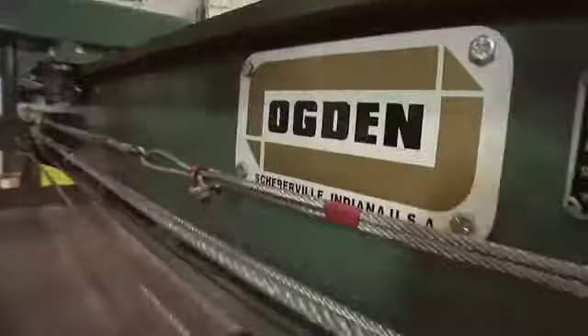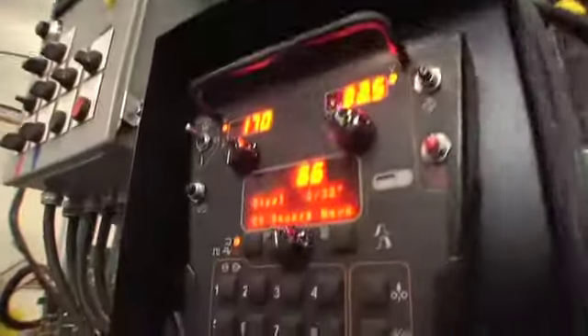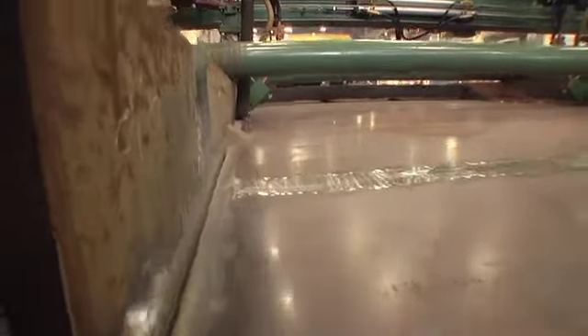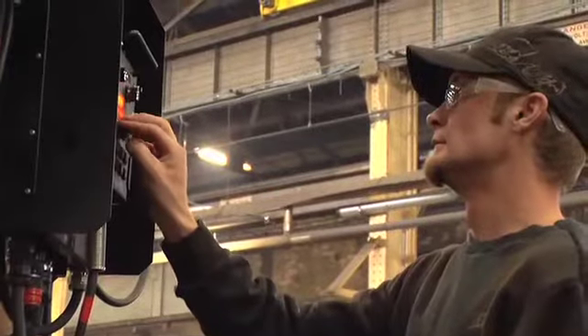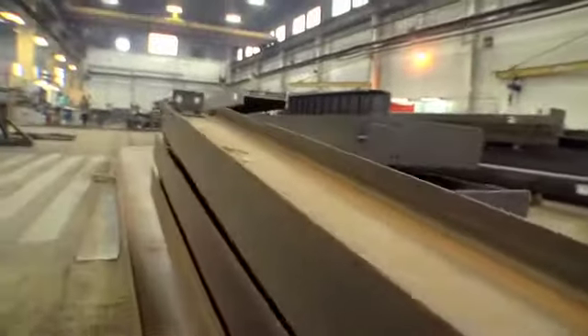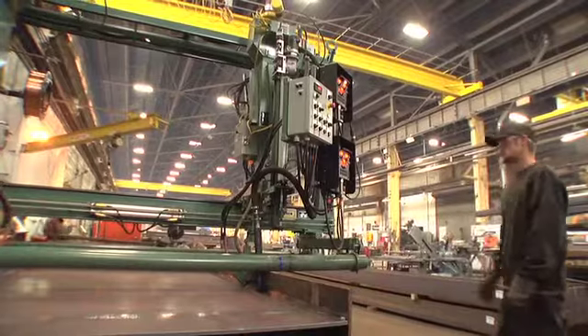They are PLC units. They're programmable logic controlled units that make up to 67-foot welds on this project, 5/16 continuous, with non-stop welding. With this technology, what it allows us to do is compete against a lot of the other fabricators that are still running the single welding machine with Lincoln LT7 tractors to run one weld bead at a time. We're actually running both weld beads down that girder at the same time, flipping the girder over, and then back welding it at the same speed. We're able to process a 67-foot long girder in right around an hour and a half, both sides. They also set up welder qualification records for all their welders, operator qualification records, and they did procedure qualification records once the WPSs were done. They were very professional in their work and their process. There's not many people around here that can do that type of work.